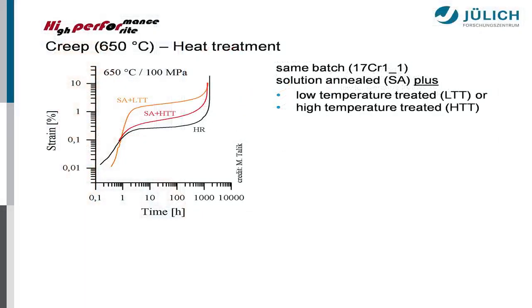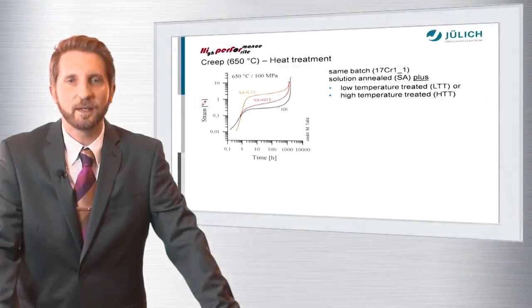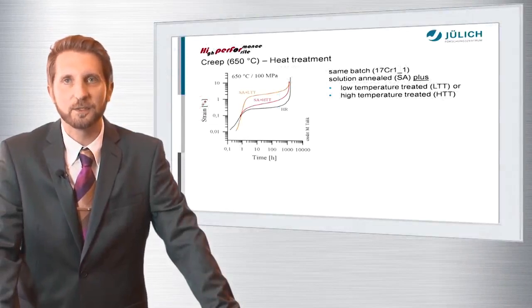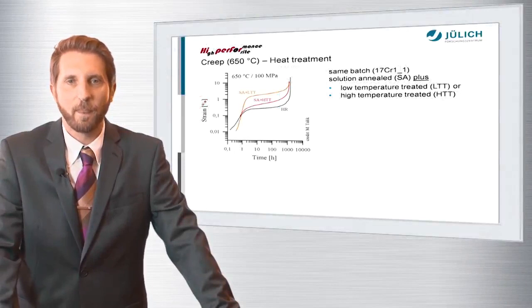This was done, for example, with a batch taken from our newest productions, and we tested it in the hot rolled state. So you have a creep curve, the black one in the diagram, that represents the creep performance of the hot rolled state, and the red and the orange curve represent the creep behavior of the same batch of the same material after solution treatment and a high temperature heat treatment added to it. That's the red curve, and a low temperature heat treatment, that's the orange curve.